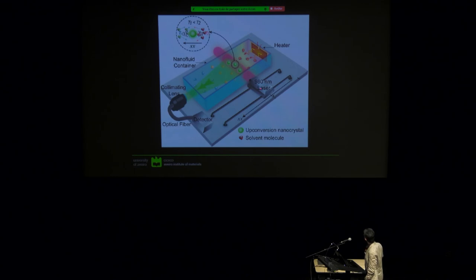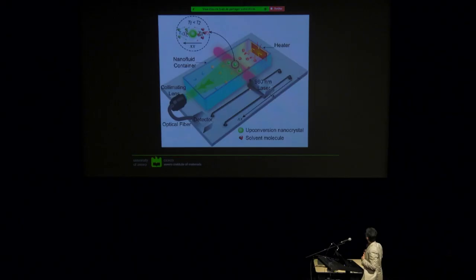And we had a laser, a 980 nanometers laser, which we could move along this direction. And then there was a detector. So we would put, say, a laser here, and we would turn on the heater. And we were taking emission spectra every so often, okay, and measuring the temperature. And at a certain point, temperature starts rising up, and then it plateaus, okay? And then we repeated the experiment, just moving the laser to another position.